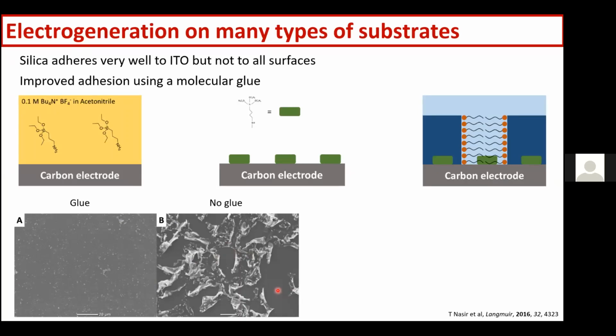If you change the substrate, for example if you want to work on gold, you change the silane, and instead of using an aminosilane, you can use a mercaptosilane to form a gold-sulfur bond on the surface of the electrode, and then you have a much better stability of your film.